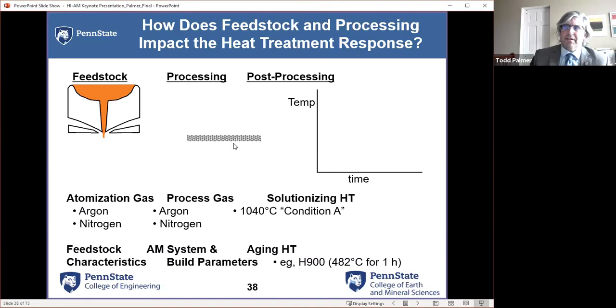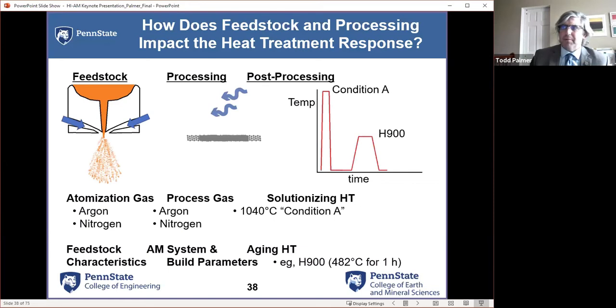I'm going to switch gears here a little bit and go to a precipitation hardened stainless steel. Now, these are some really common ones that are out there. And what these steels require is post-processing. So going back to the powder feedstock and what gas we're choosing for that atomization gas, the processing gas, we hear a lot of people talk about processing gas, but we've found, especially in powder bed fusion, that it's not quite as important or as big of a factor as this atomization gas. This is a way to introduce large amounts or really cut back on the amount of diatomic gases you may have in your feedstock. But all of these impact post-processing.